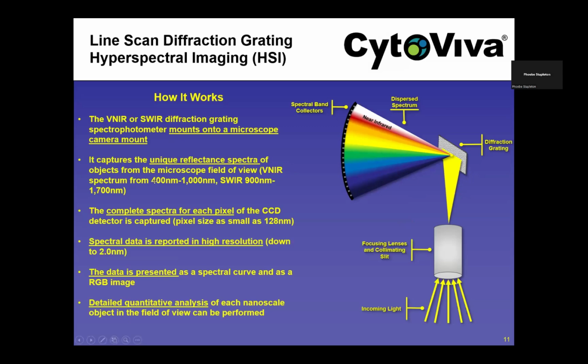And in the VNIR range, we're capturing data from 400 nanometers early in the visible, all the way out to the near infrared at 1,000 nanometers, or in the shortwave infrared range, 900 to 1,700 nanometers. And that data is captured in every single pixel. And pixels can be very small. They can be right at 0.1, 0.12 microns with a 100x objective, for example. And in each pixel, you've got, for example, all of the VNIR data from 400 to 1,000 nanometers.